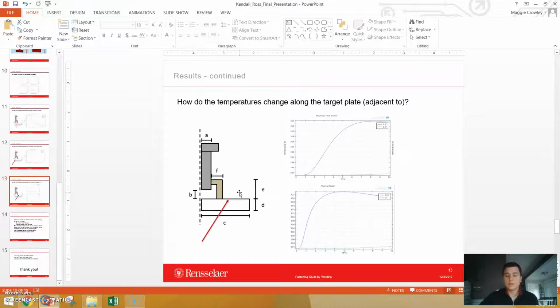But basically what I found using these models was that the temperature along the top of the target plate really wasn't getting very hot, which shows that these studs can be welded pretty close to adjacent temperature sensitive material. So that's good.